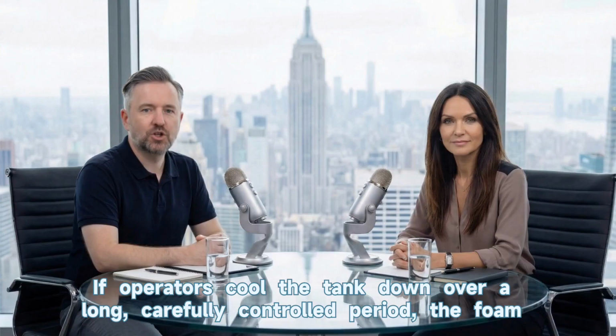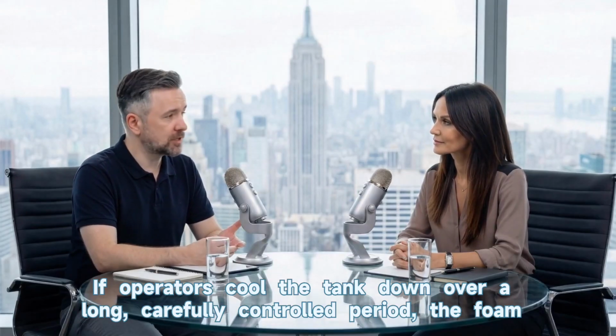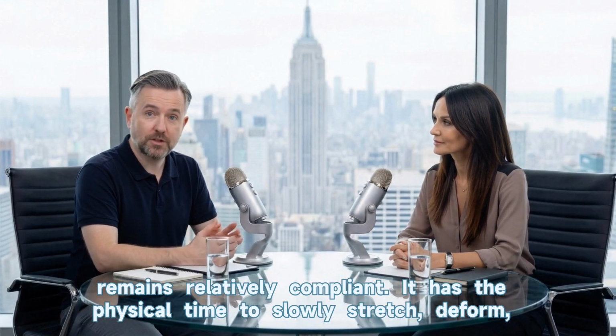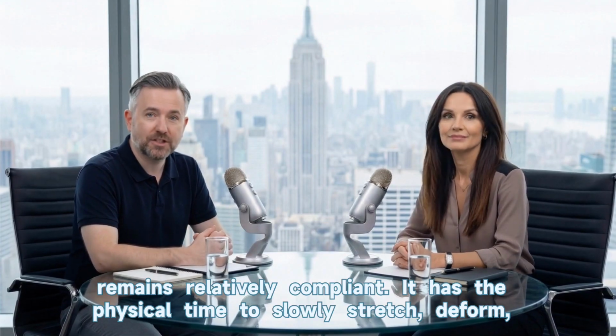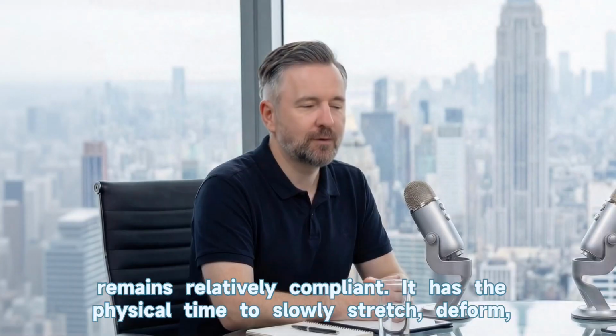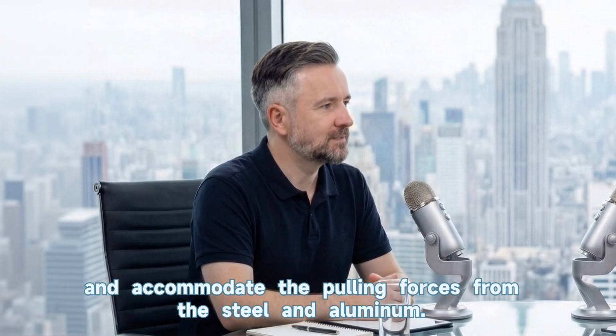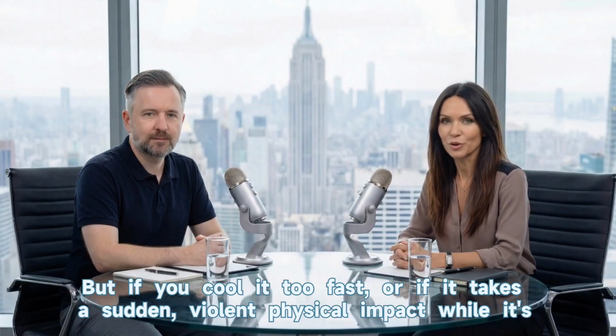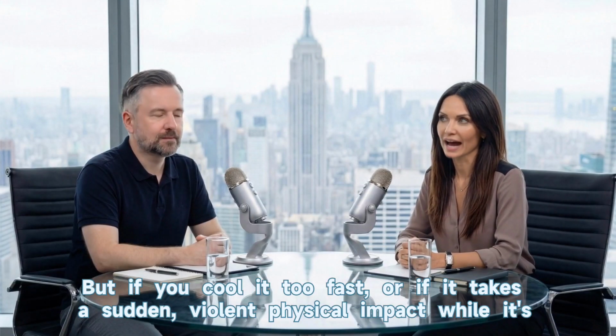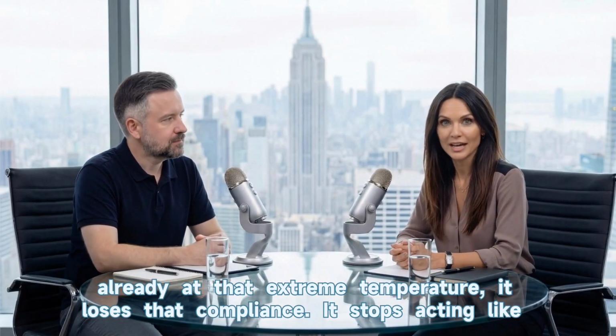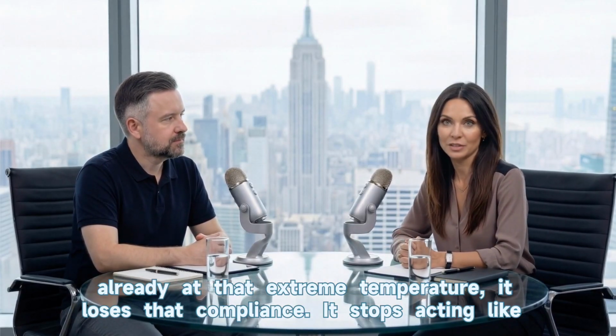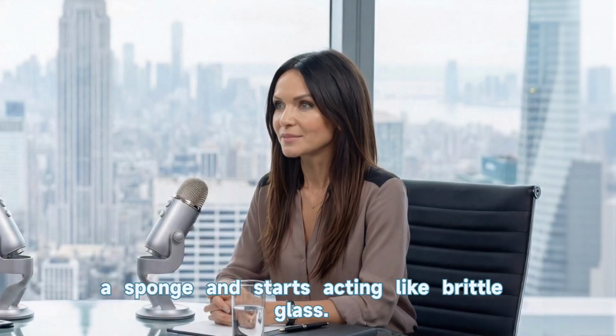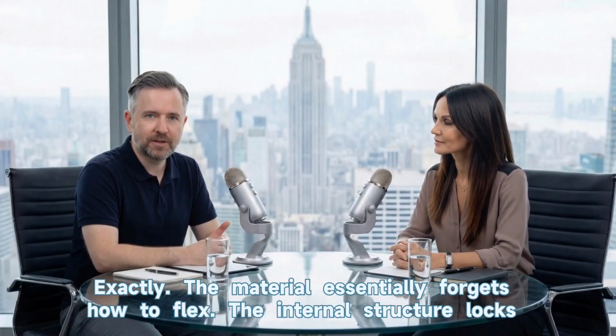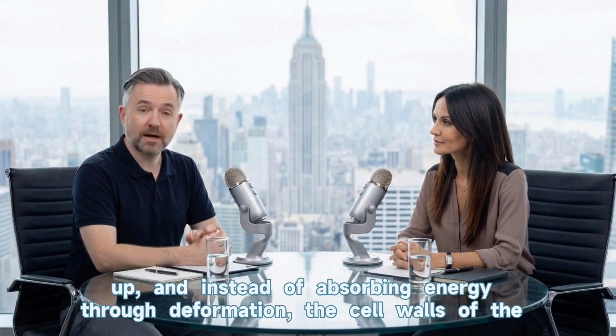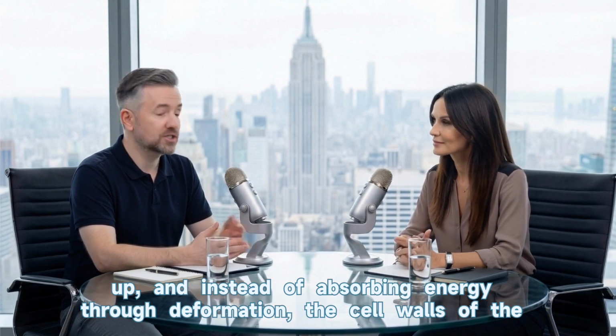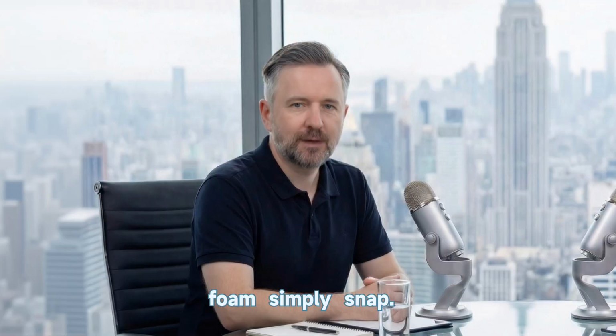Okay. If operators cool the tank down over a long, carefully controlled period, the foam remains relatively compliant. It has the physical time to slowly stretch, deform, and accommodate the pulling forces from the steel and aluminum. But if you cool it too fast, or if it takes a sudden, violent physical impact while it's already at that extreme temperature, it loses that compliance. It stops acting like a sponge and starts acting like brittle glass. Exactly. The material essentially forgets how to flex. The internal structure locks up, and instead of absorbing energy through deformation, the cell walls of the foam simply snap.